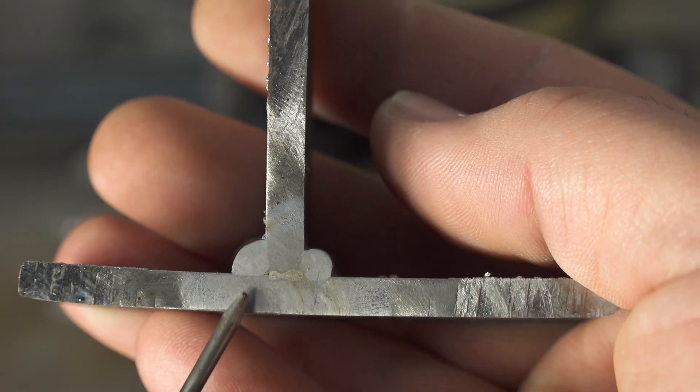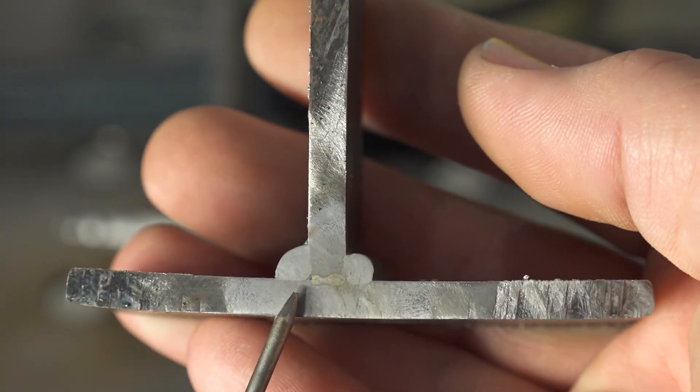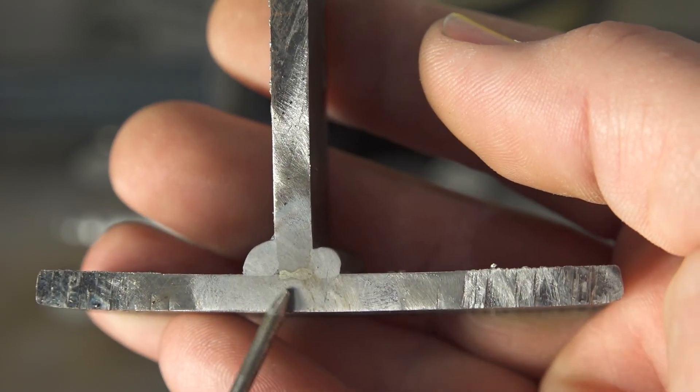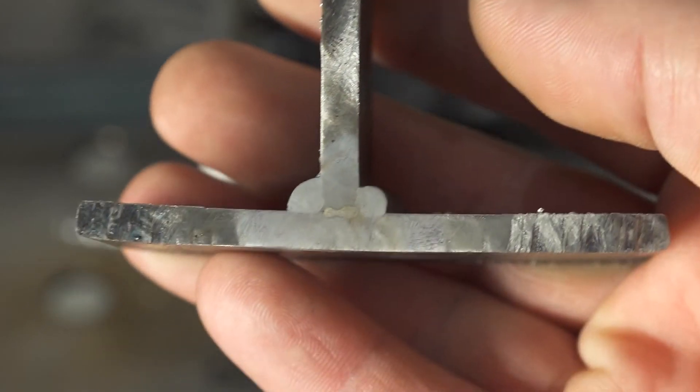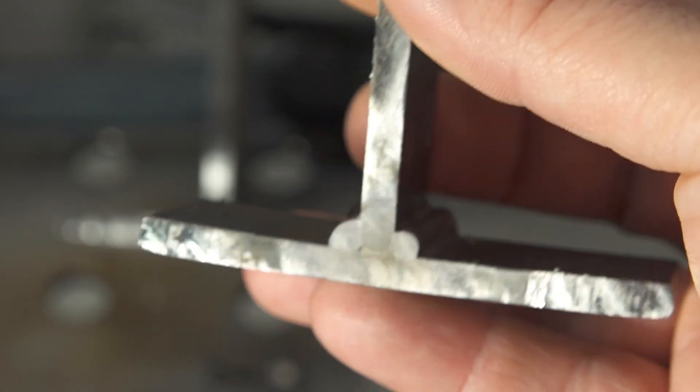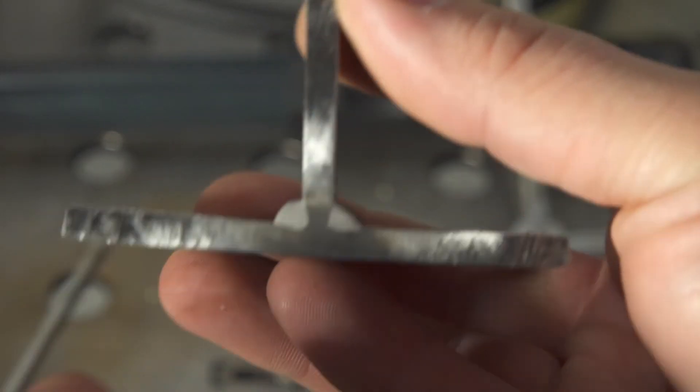Virtually no tie-in on this bottom piece and only the tiniest bit on this vertical section. So again this is how the welder did originally with AC output, really high crowned welds, not a lot of penetration, not getting down into the root. Like I said this was about the best I got on 3/16 material with the welder stock.